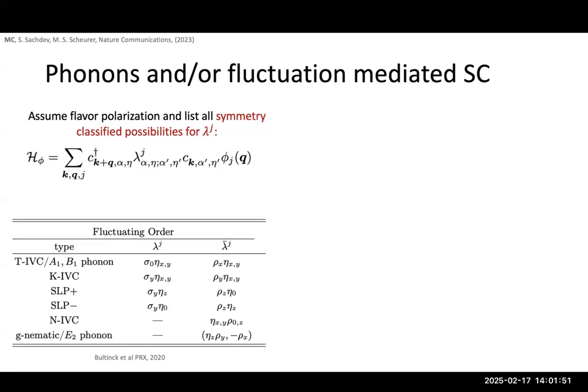So what are these possibilities? One of them is a time reversal symmetric intervalley coherent state. This is a state which doesn't break time reversal symmetry, but breaks the U(1) valley symmetry. So it hybridizes the two graphene valleys of the problem. And symmetry-wise, this is indistinguishable from a type of optical phonon that you get from graphene that scatters also between the two valleys.